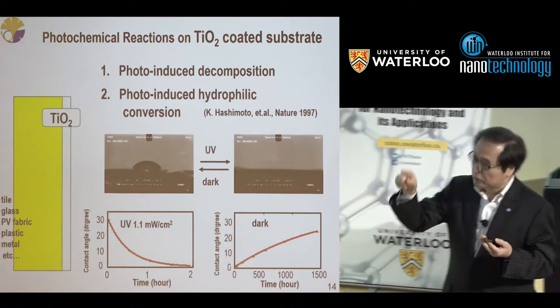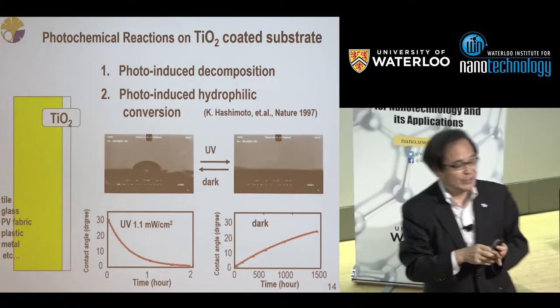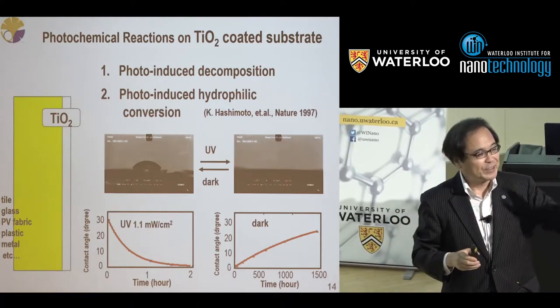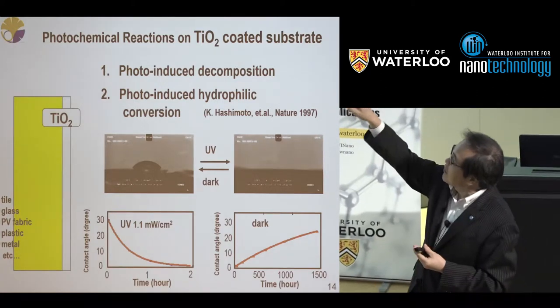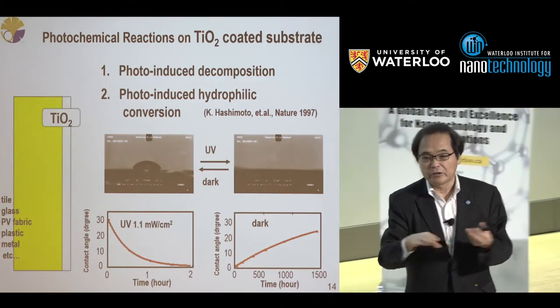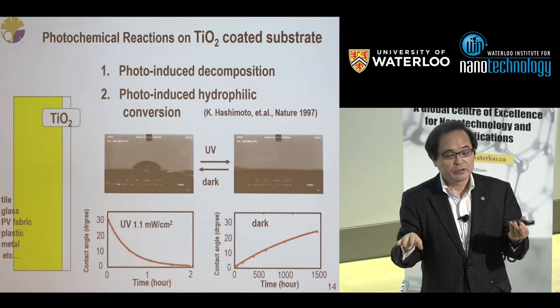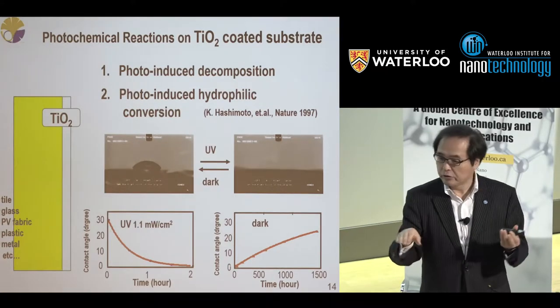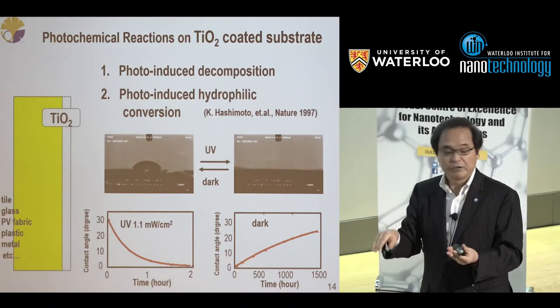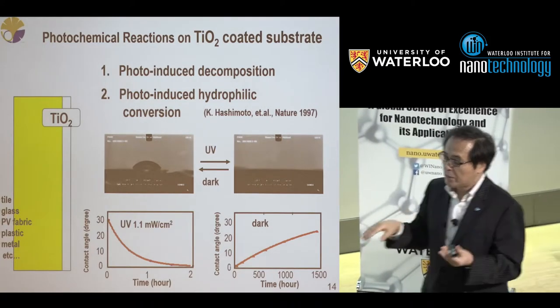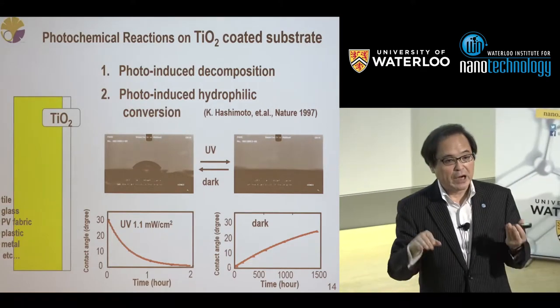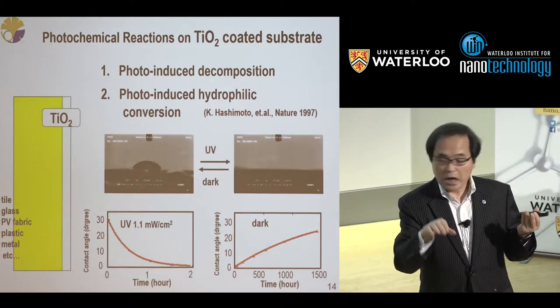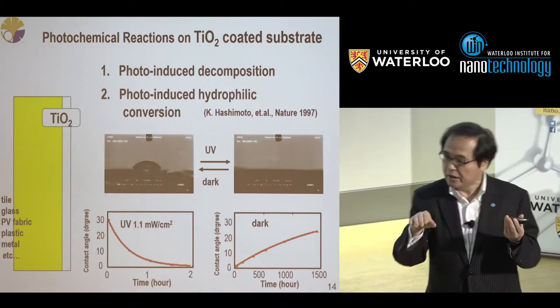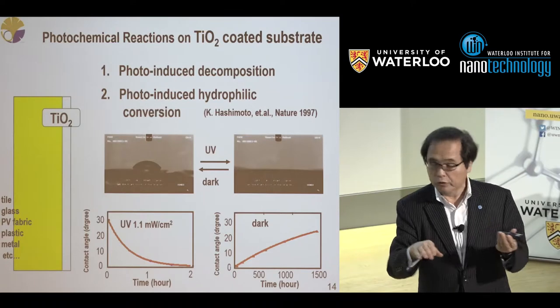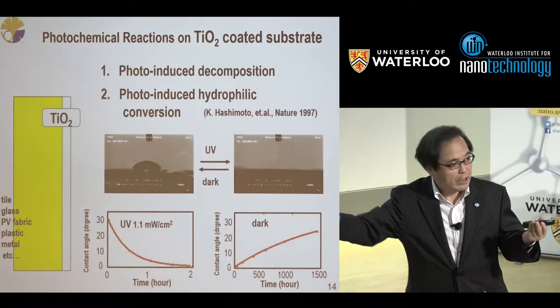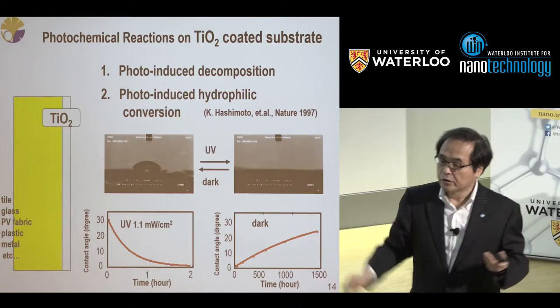Before the illumination, the water droplet's contact angle, which was explained clearly yesterday, is about 30 degrees or something like that for conventional titanium dioxide coated materials. But after illumination, the contact angle becomes zero degrees. Superhydrophilic in this case, not superhydrophobic. The superhydrophilic state is obtained by weak UV light illumination. And such a hydrophilic state is maintained even without illumination for several hours or several tens of hours, and returns to the original situation gradually.